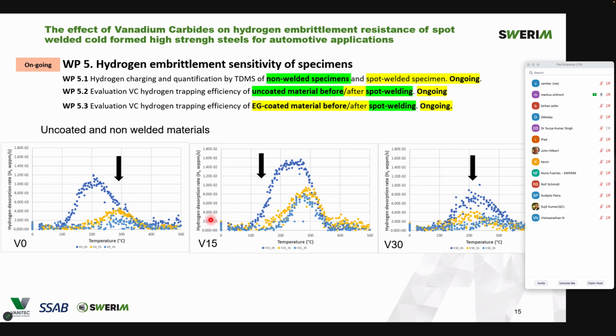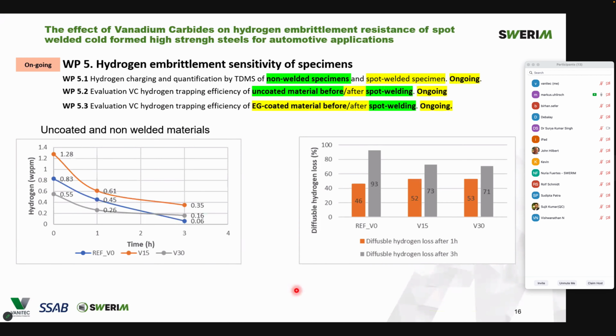Then we left the samples at air for 1 hour and for 3 hours at room temperature. After 1 hour, we could see that the hydrogen content has decreased for all of them, that's the yellow curve. After 3 hours, it has decreased even further. In the following slide, we summarized those values in numbers so it's a bit easier to see. So here in the graph on the left, we see the gradual decrease of hydrogen when leaving them at air for 0 hours, 1 hour, and 3 hours. We calculated the loss of this diffusible hydrogen.